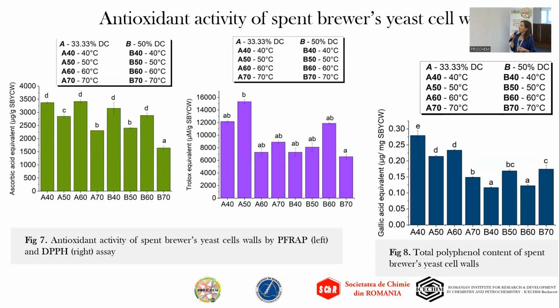We also assessed the antioxidant activity of spent brewer's yeast cell walls. Using the same methods, the trend of the samples was the same for both duty cycles used according to the FRAP assay. Also, using the DPPH method, we obtained an optimal of 50 degrees Celsius for the highest antioxidant activity of the spent brewer's yeast cell walls.